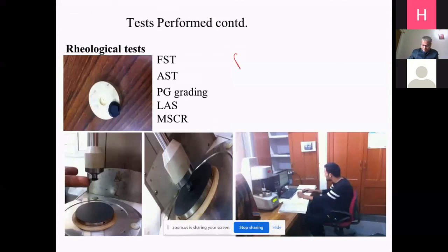Rheological tests are the new things in the country now. Worldwide, people are not using penetration tests or softening tests nowadays, which are indirect measures of viscosity. What we measure in the penetration test is the penetration in 1/10 of mm, which is not the viscosity, which should be in poise. Similarly, in the softening point, we measure the temperature at which the balls touch the lower plate. That is also not the viscosity, that is in degrees centigrade. Thirdly, in other tests, we find out the length at which the thread breaks. That is in centimeters, not in poise.